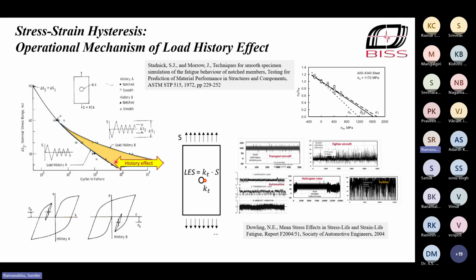And it becomes predominant as your life goes higher and higher towards the endurance limit, which means that it's the fatigue limit that is affected. And amazingly, they also laid the foundation with this experiment for notch fatigue analysis, because they showed that you can take a smooth specimen and apply the same stress strain history, and it will show you the same effect. That's why the data points from smooth specimens and notch coupons are shown on the same plot. And that is the graphic representation of what happens to the mean stress when you apply an overload.